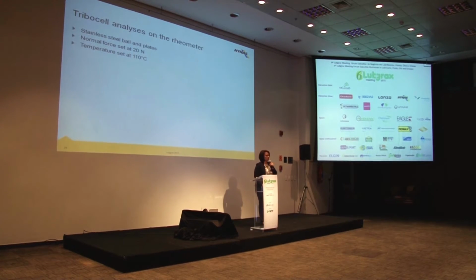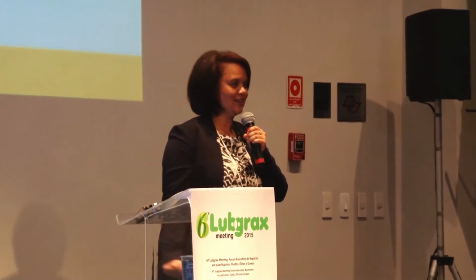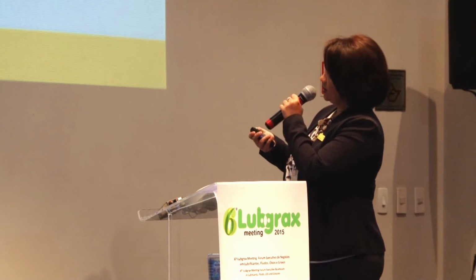Right. So I wanted to understand how the oils would behave in the same kind of test rigs, but unfortunately we had to just use what we had at our disposal at this point of the project. So we did have a rheometer, and I had a tribology attachment to the rheometer, so I was able to run Stribeck curves on a rheometer. The setup here is a steel ball and 3 plates, and I set the same force of 20 newtons, and we used the same temperature of 110. These are not the right plates, but I had metal plates here, so you've got 1, 2, 3, and the ball, and then you submerge it in the oil, and you can generate Stribeck curves from this instrument.